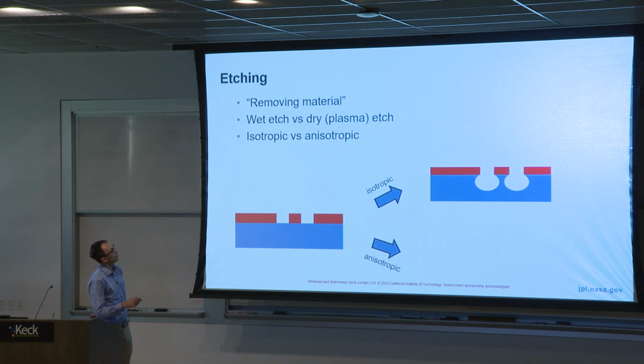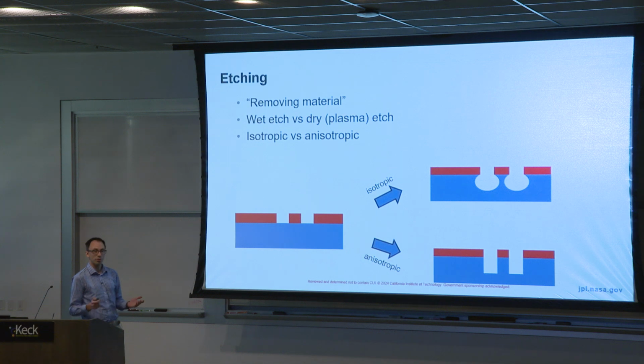In contrast, plasma etching can be highly anisotropic. So wet etching is typically isotropic. There are a few notable exceptions, but they're very specialized, so let's not go into them. Plasma etching can be very anisotropic. And I say can be because if you've worked for a little while with etching, you know that it's not always going to be the case. It's highly material dependent, and you often have to work for quite a while to make sure that your etching is as anisotropic as you desire it to be. But in a perfect world, this is what you do: you have your pattern and you perfectly transfer that in a completely vertical, anisotropic manner into the substrate or into the material below.